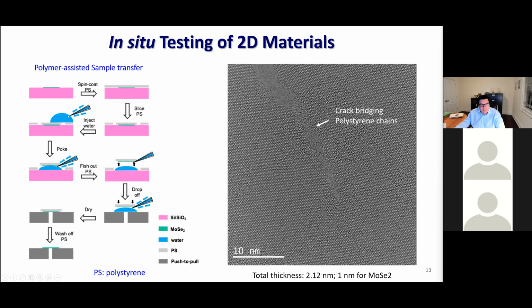And then using a micropipette, deliver water and lift the polymer with the monolayer and then place it on top of the silicon chip and dry it and remove the polymer. But for removing the polymer, there are different solvents that you can use, or you can use thermal annealing. What we found is that it's never perfect. It always leaves a very thin layer of polymer on top of the 2D material.